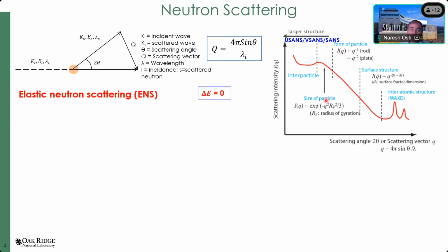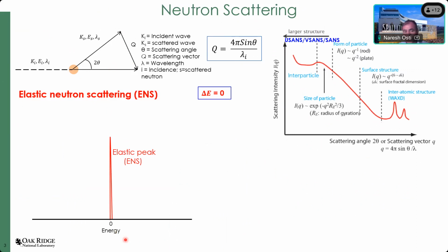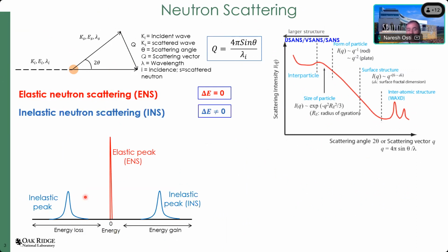On the other hand, if you plot the scattering intensity as a function of energy transfer, in the case of elastic scattering, you will end up with a peak centered at zero energy transfer, which we call the elastic peak. Now, the situation would be different when you have a finite energy exchange between the neutron and the scattering sample. At that time, you will end up getting the inelastic peak in both the energy gain and the energy loss axis of the spectrum.